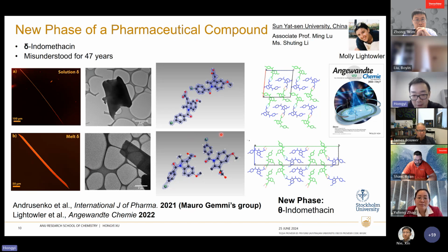Actually, it took a very long time to solve the structure of this polymorph because of the large unit cell and the disorder in the structure. So only with MicroED could we look at the small crystals and actually distinguish that these two are different polymorphs. And this was a question that was unknown for 47 years. So that was quite a nice showcase of polymorph discovery and of detecting new polymorphs in pharmaceutical compounds.